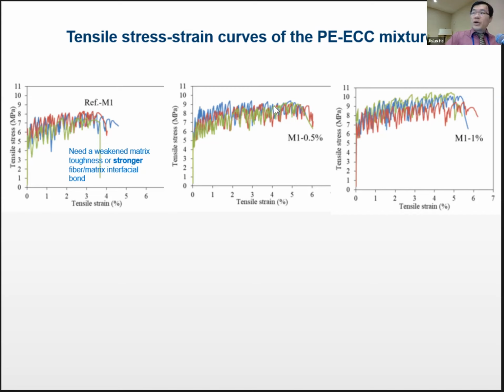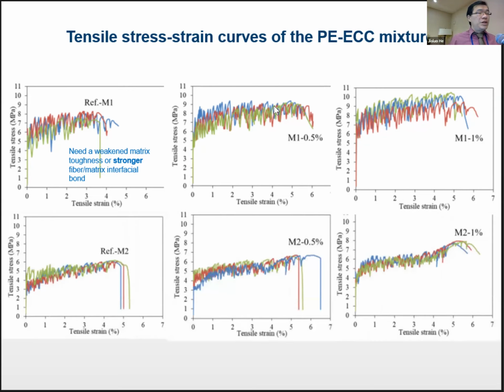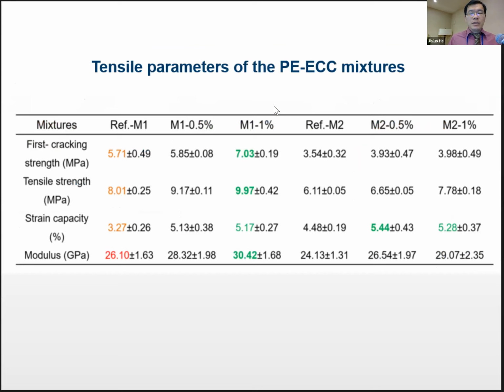So in terms of stronger bond, you can see once you add nanosilica, you are achieving stronger bond. Therefore, you're getting better ductility and better tensile behavior. Or you can use a weaker matrix. In the case of high volume fly ash, you have a weaker matrix, you're achieving better ductility. For instance, especially this one, you can achieve 5% or 6% ductility, which is very bendable concrete. So here's a lot of quantitative information derived from those curves, the tensile stress-strain curves.